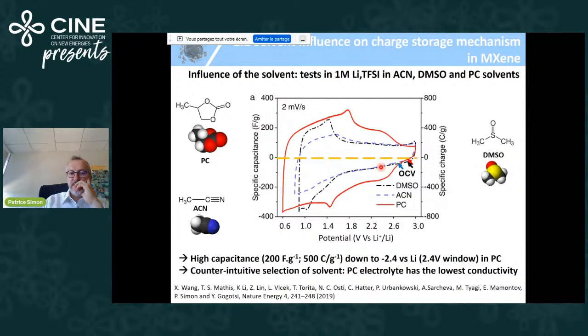In blue and black, this is the cyclic voltammetry in acetonitrile and DMSO electrolyte. You can see that we have a small capacity and, I would say, a blurry electrochemical signature. However, when you use PC, you see that you have an opening of an electrochemical voltage window with lithium intercalation, and you have very decent cyclic voltammetry. You have a very good charge of 500 coulomb per gram, which is about 200 milliamp hours per gram, and you intercalate lithium from 2.6 down to 0.6 volt within a 2.4 volt window, which is one of the first times. It was the first report of very decent electrochemical activity in non-aqueous electrolyte from MXenes. But more, this is a counterintuitive selection of solvent because PC electrolyte has the lowest conductivity.